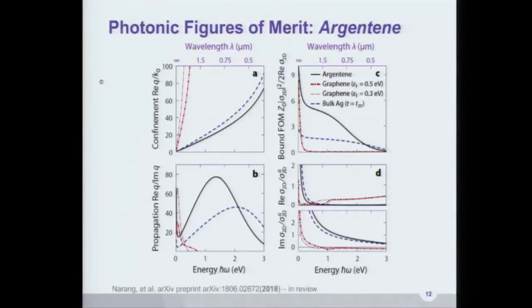Okay, so with everything that you say could be low loss, people in photonics have told me that you need photonic figures of merit, and not just a figure of merit. Everyone in photonics has their own figure of merit, so you need all of the figures of merit always. And here we're comparing confinement or propagation. These are my two favorite figures of merit. There are a few others if you think about the ratios of the sheet conductivity, the imaginary and the real parts. But confinement and propagation are easy to think about because you want things to be very confined, because the less confined they are, the more you're getting a situation where you're not coupling in as much. You also want them to propagate for a really long time. So you launch here, and then it keeps going for, I don't know, miles or maybe hundreds of miles.